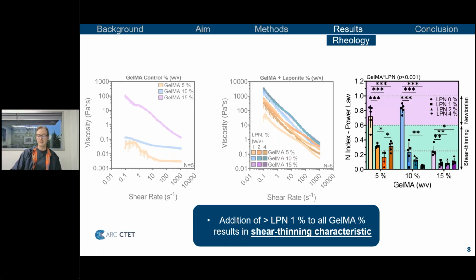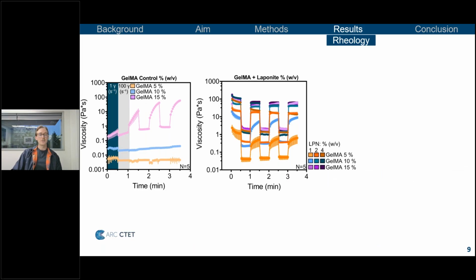What we can see here is that the addition of more than 1% laponite to GelMA results in enhanced shear thinning capability. We then looked at the thixotropic test, which is applying different shear rates to mimic the extrusion of the material being extruded, and to look at its shape recovery when these different shear rates were applied. Again, looking at the GelMA controls for 5 to 15%, we can see a drop in viscosity and a change when these shear rates are applied.